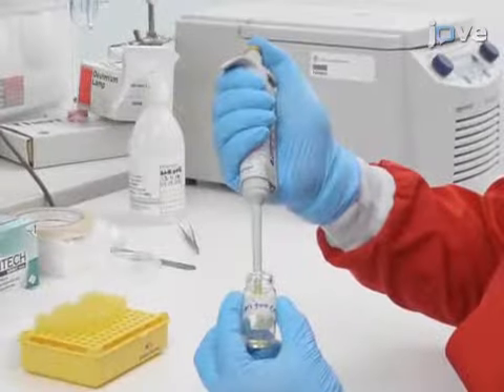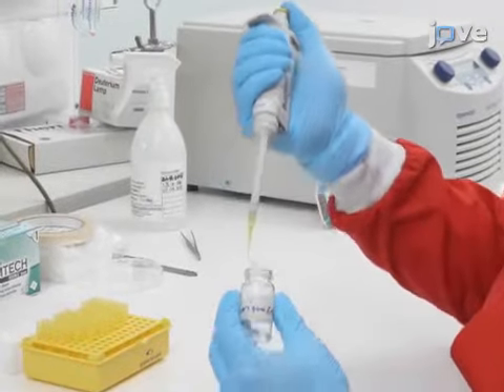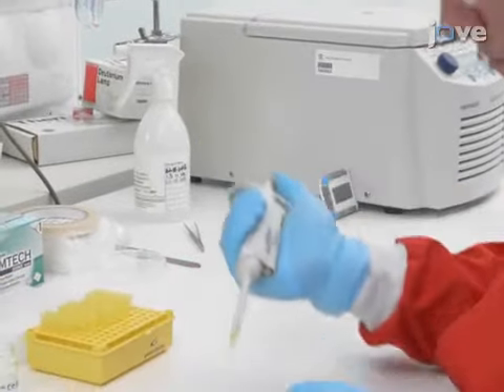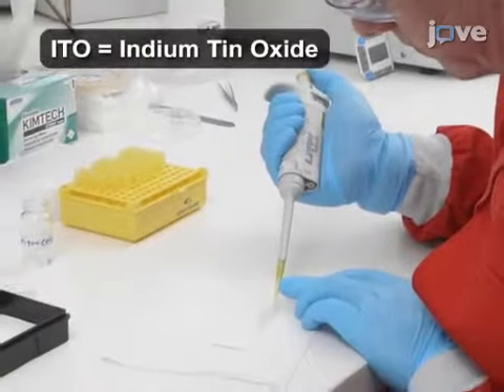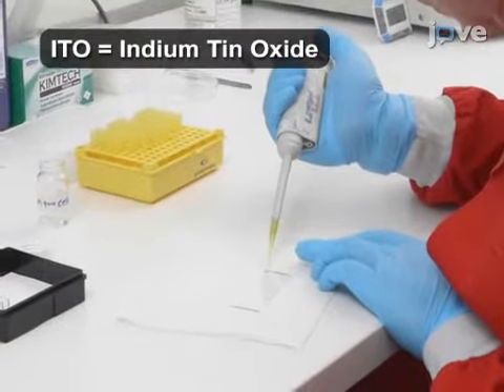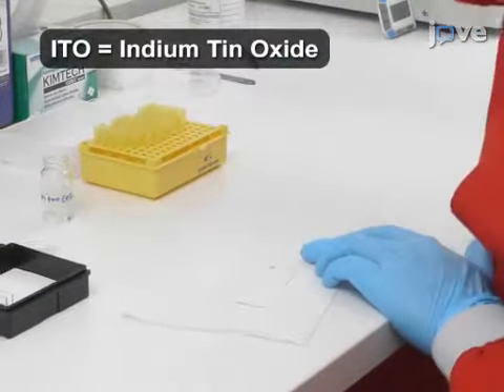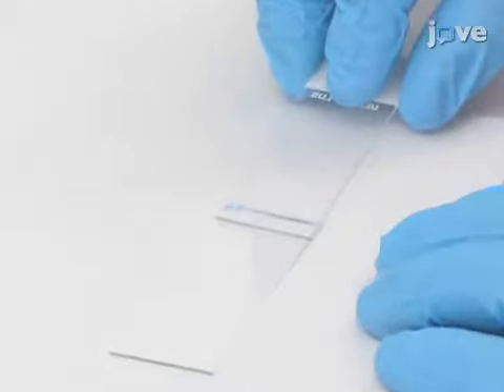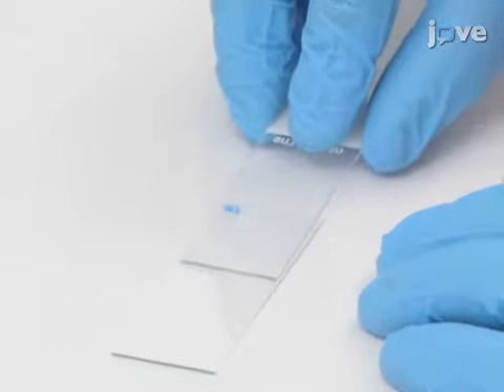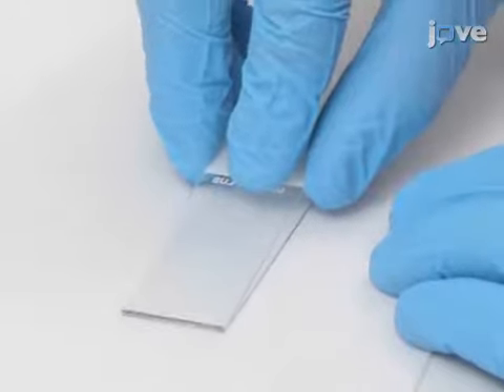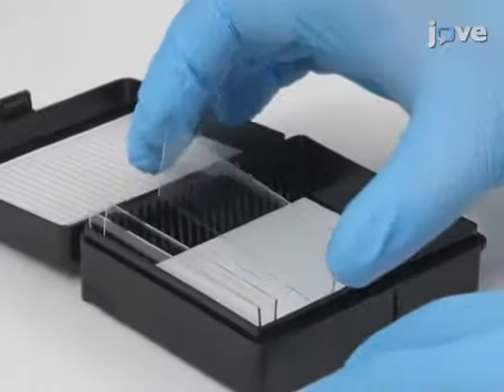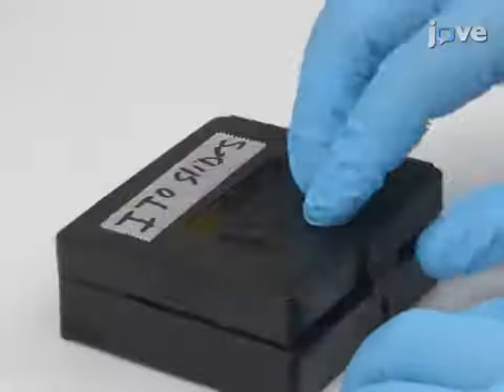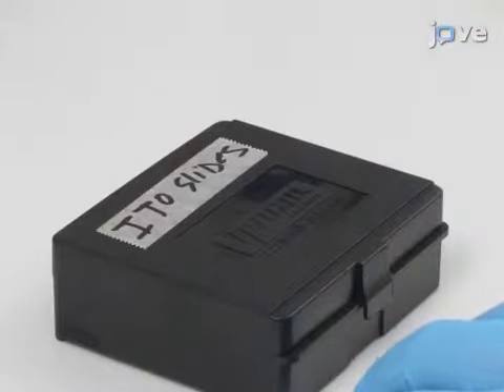To prepare the nitrocellulose-coated slides, pipette 40 microliters of liquid nitrocellulose onto one edge of a conductive indium tin oxide microscope slide. Using a regular glass microscope slide, drag the nitrocellulose under surface tension across the slide to create an even thin film coating. Allow the nitrocellulose to dry at room temperature for 20 seconds and then store until needed